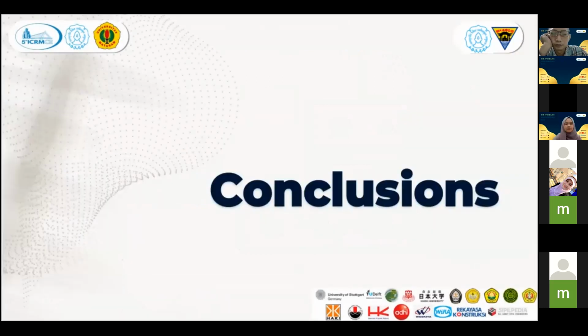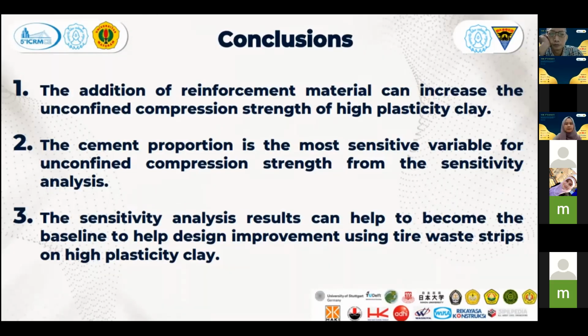And this is the third part, conclusion. The first conclusion is the addition of reinforcement material can increase the unconfined compressive strength of high plasticity clay. The second conclusion is the cement proportion is the most sensitive variable for unconfined compressive strength from the sensitivity analysis. And the third conclusion is the sensitivity analysis result can become the baseline to help design improvement using tire waste strips on high plasticity clay.